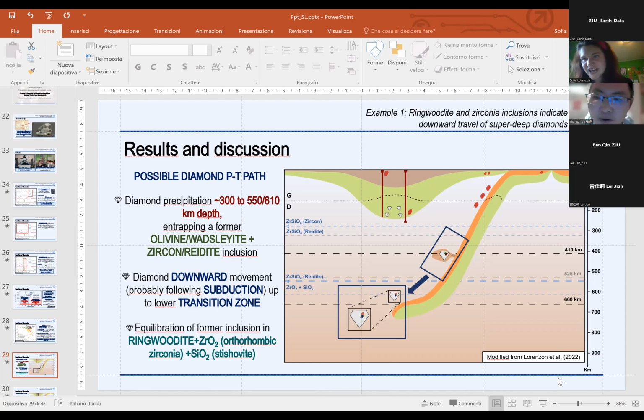Sorry, can you repeat that? The water content of the ringwoodite. The water content, sorry. Okay, the water content is a very good question. At the beginning of this study, when I found ringwoodite, the first thing that I and the other people who collaborated with me thought was that we absolutely must try to determine the water content of this ringwoodite. But the problem with these inclusions is that they are too small, and the best way of calculating the water content is FTIR analysis, as you probably know. But performing FTIR analysis on an inclusion so small and so deep within the diamond is not easy.